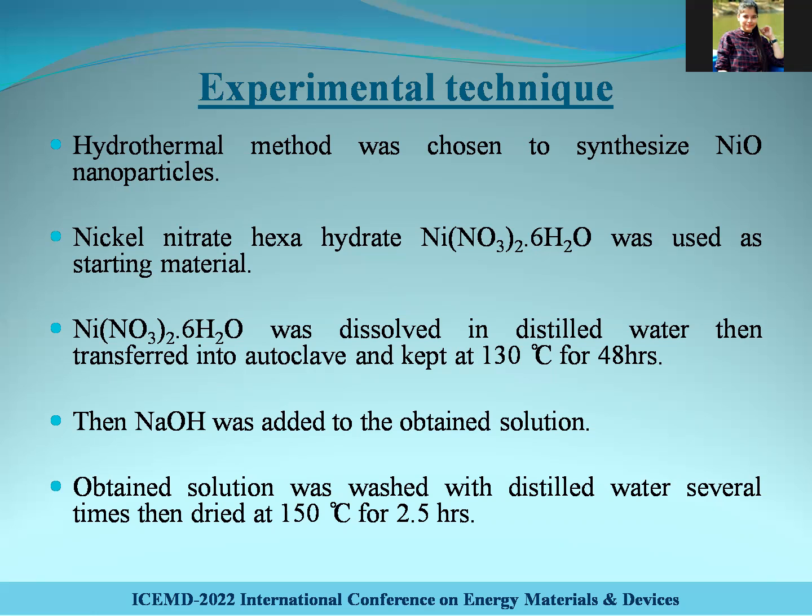NaOH was added to the solution, and then the obtained mixture of nickel nitrate and NaOH was washed with distilled water several times and then dried at 150 degrees centigrade for 2.5 hours.